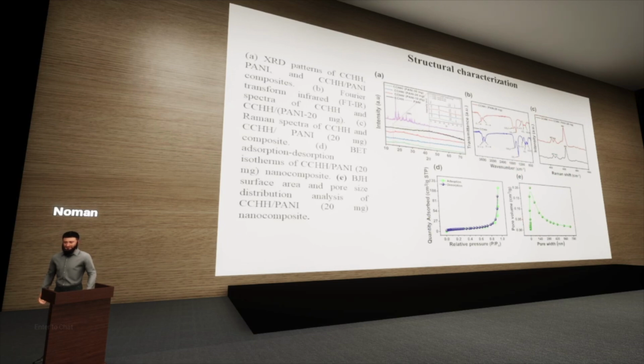This is the structural characterization of the synthesized material. This is the XRD of the four compositions. We synthesized the cobalt carbonate hydroxide hydrate, and then added the polyaniline in various concentrations, 10 milligram, 20 milligram, and 30 milligram, to find the optimized value. This is the XRD pattern of polyaniline and all the compositions, and the clear peaks for the addition of polyaniline, and the clear peaks for the identification of the planes for cobalt carbonate hydroxide hydrate are shown here.